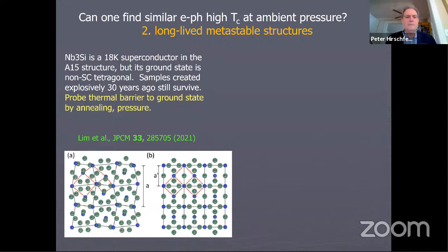There are a couple of papers that we've been involved with in my group in the past few months, which I think are interesting. One is niobium-3 silicon, which is a classic material that was very similar to materials that form in the so-called A15 structure, which are among the highest TC conventional superconductors, but it's not superconducting in its ground state for some reason.